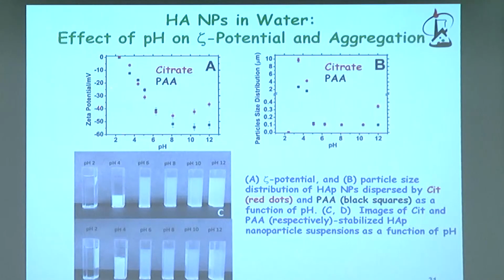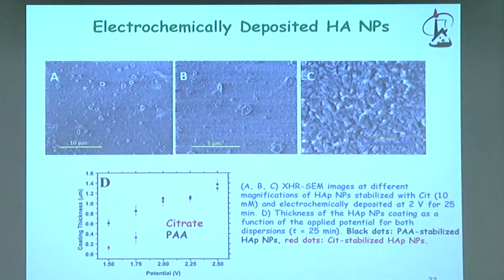Okay? And here you can see how the zeta potential changes as a function of pH. Obviously, as you go to a pH lower than the pK of the carboxylic acid, the zeta potential becomes close to zero. And you can see also here that the size of the nanoparticles obviously increases. So here you can see this is the deposition, okay?